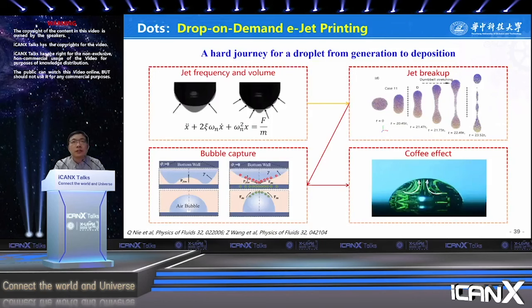It is still a hard journey to merely print a drop. There are four important issues that have to be addressed, including the jetting frequency and the volume during the generation, the jet breakup during flying, the bubble captured during the deposition, and the coffee ring during the drying. As shown in the top left figure, one can adopt high-order resonance to improve the jet frequency and the volume. Certainly, the frequency and the volume are also related to the viscosity of the solution, the diameter of the nozzle, and the strength of the electric field.